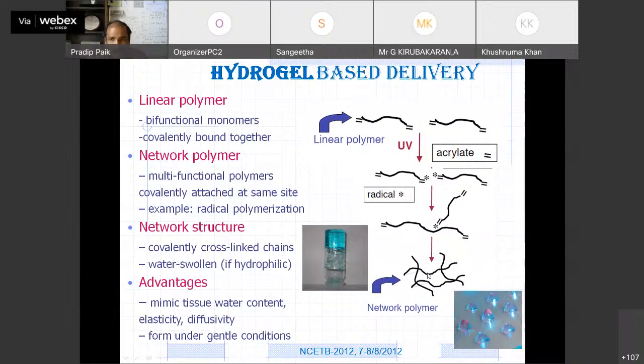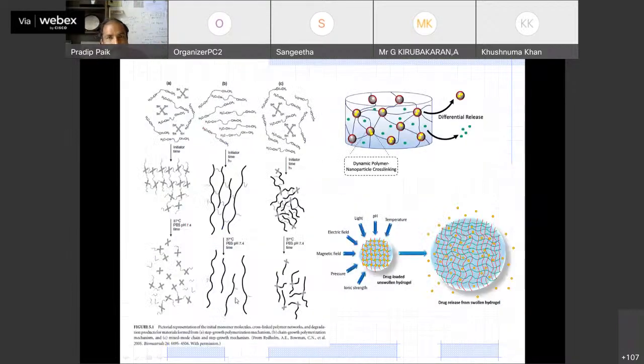So if you have a core, then on the surface of the core there will be hydrogel. The hydrogel property is that whenever you put it inside water, it will expand. Almost 90% volume will be increased, and that increasing volume will help to release. If it is not released, if it is there inside this core, then you have to give a little bit of stimulus or push. So network formation advantage you can make above the surface of the core, let's say a solid core. This is a secondary advantage.